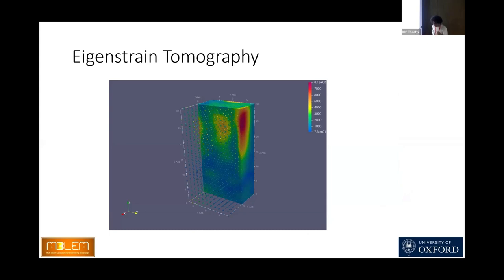And this is the result. Full-field distribution of residual stresses in additively manufactured body reconstructed using strain tomography technique with very limited number of data. Here results are given as magnitude sum of nine stress tensor components.